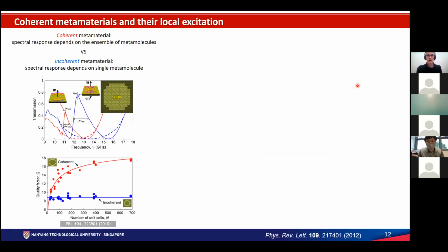The first material we looked at, and quite successfully, is what is called coherent metamaterial. Coherent metamaterials are a special kind of nanostructured materials where the spectral response is not dictated by the single resonance of the single element, the single atom of the material, but from the ensemble of it. As you can see here on the bottom, for an incoherent metamaterial, you have the same quality factor of the resonance, independently of the number of unit cells that you're illuminating. This is through far field illumination with a plane wave. While if you do the same thing with a coherent metamaterial, the quality factor becomes better and better. This is because the mode supported by the coherent metamaterial is actually a magnetic dipole that is perpendicular to the surface of the material. Therefore, the emission happens on the surface. It cannot easily decouple out, and you engage a collective mode out of it.